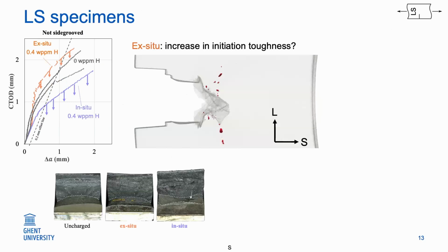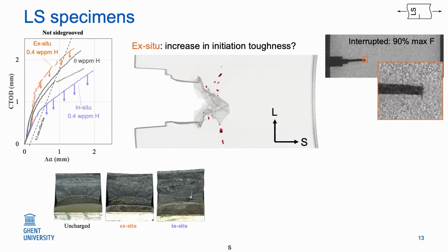And then finally, the LS. So now we are growing our crack not along the bands, but actually right onto the bands. And what happens now is that ex situ we actually get an improved curve. But this is, well, a bit of an illusion, because what happens is there is a split actually happening right at the end of the fatigue crack. So you can see when we interrupt it at 90% maximum force, so before maximum force, not after, right at the end of the fatigue pre-crack, there is a split happening.